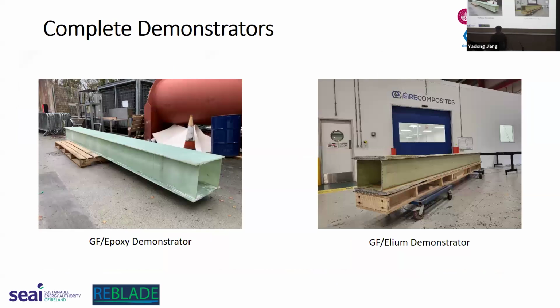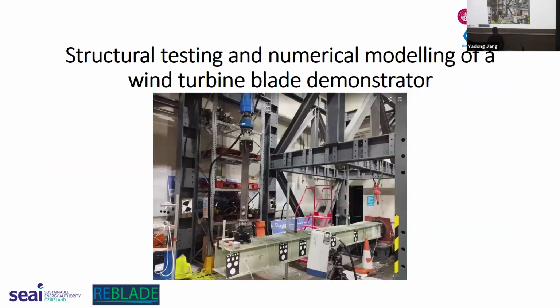And then we have the two completed demonstrators: the glass fiber epoxy demonstrator on the left and the glass fiber Elium demonstrator on the right. You can sort of see a color difference. The epoxy one is a little bit greener, and the Elium one has more of a yellow tint to it. So now I'll hand over to Yadong for the structural testing of the demonstrators.